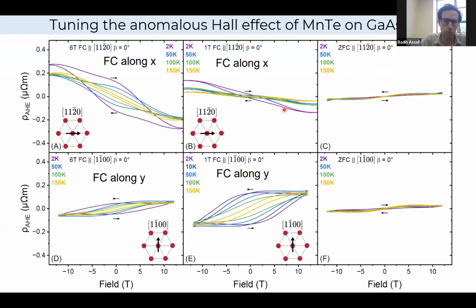So I'm going to reiterate this and show you a few more extensive measurements before I conclude. Essentially, when we grow MnTe on gallium arsenide, we find that there's almost no anomalous Hall effect without field cooling. These are the two data sets shown here. And then if we field cool along X or along Y, we start to open a loop and we start to observe a spontaneous anomalous Hall effect, whose quantitative details actually depend quite sensitively on how you apply your magnetic field and also on its strength. And it turns out these details also vary from sample to sample quite a bit.